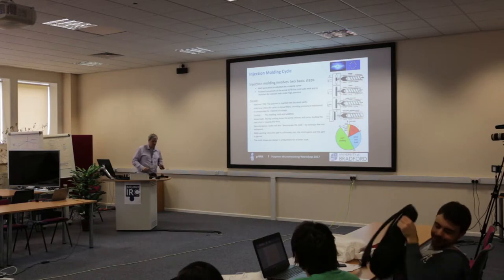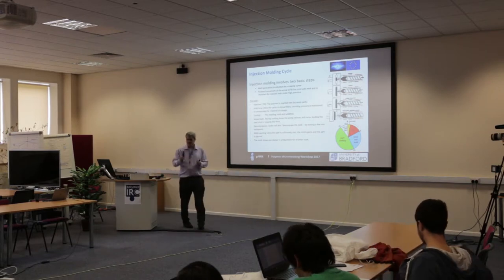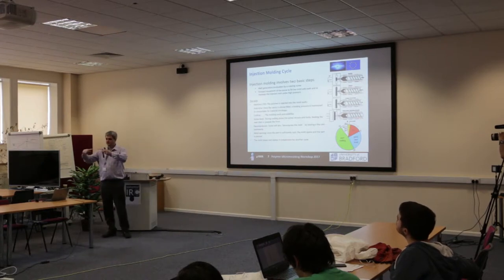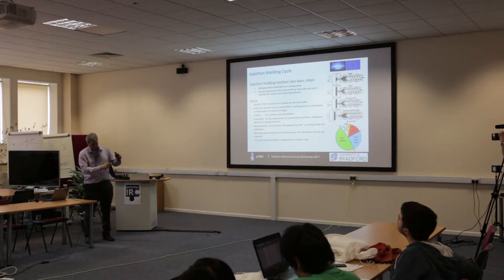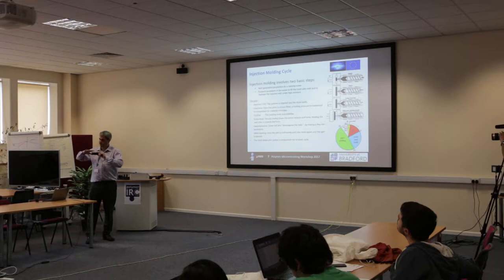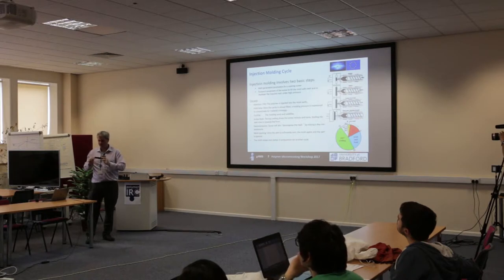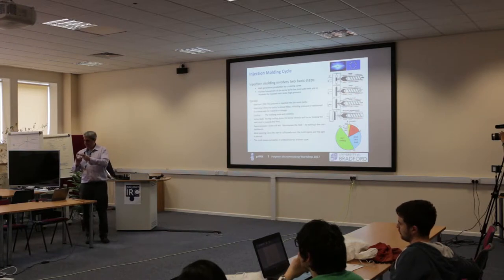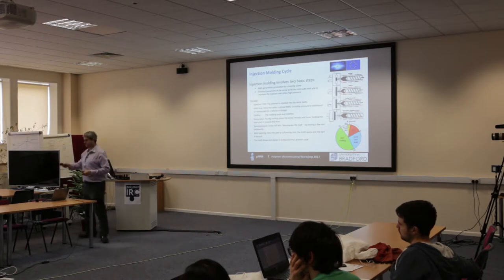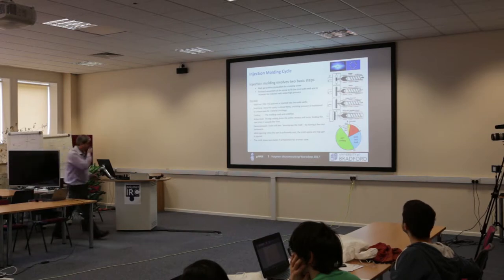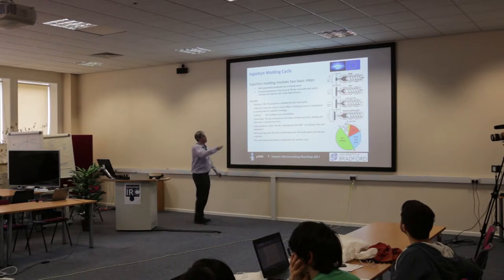Imagine the part cooling from contact with the mold surface — you get a kind of sandwich structure with a frozen layer on the outside and a soft molten core. By keeping that core under pressure we account for the shrinkage behavior. A simple injection-molded test specimen illustrates this: you can see the sprue at the nozzle tip, the split plane, and little circles on the back indicating ejector pin locations. Where there's a rib junction or thicker section on the back, you can actually see a slight indented area — a visual indicator of this shrinkage process.